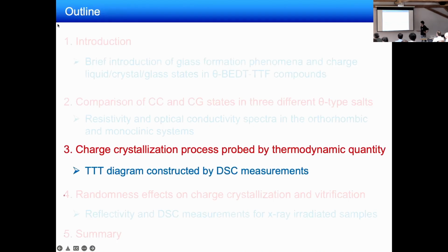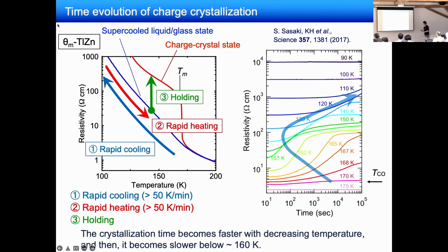Okay, so next I will talk about the charge crystallization process probed by a thermodynamic quantity. In the present system, the amplitude of resistivity reflects the charge crystallization progress, because in the charge liquid or glass states the resistivity becomes low, but in the charge crystal state the resistivity becomes very high. So in this study, in order to investigate the charge crystallization progress, we first cooled down the sample to low temperature, and then heated the sample up to a certain temperature, and kept that temperature during the charge crystallization progress while measuring the resistivity as a function of time, like this.